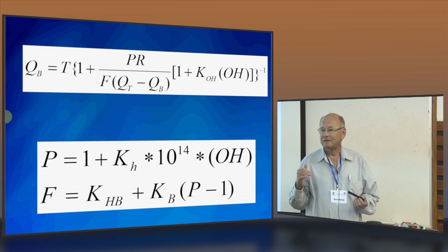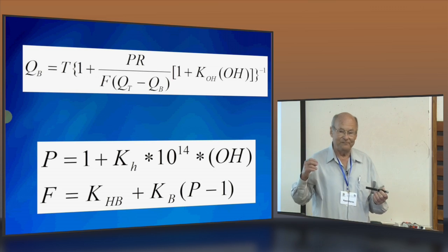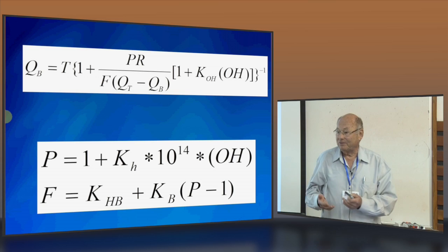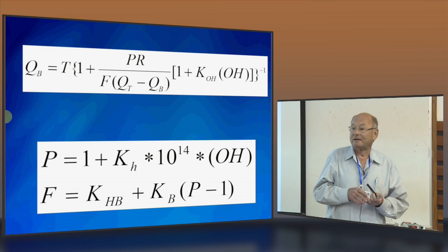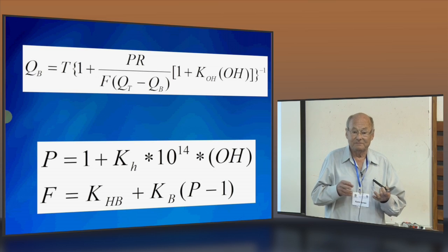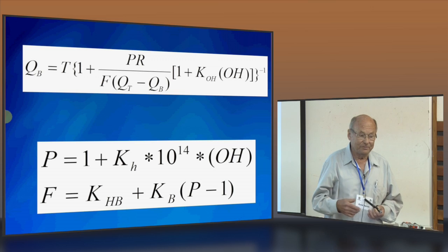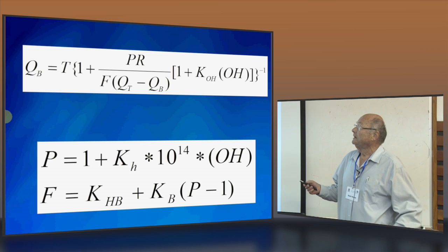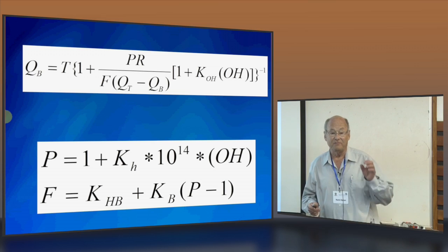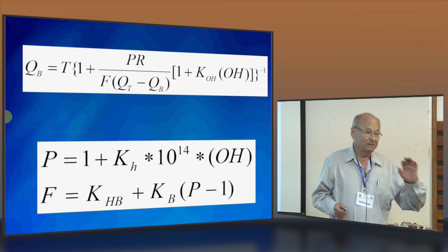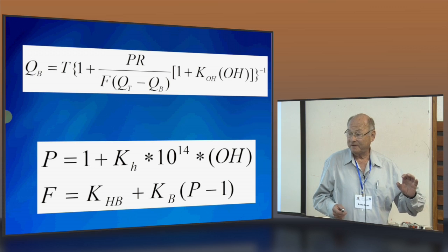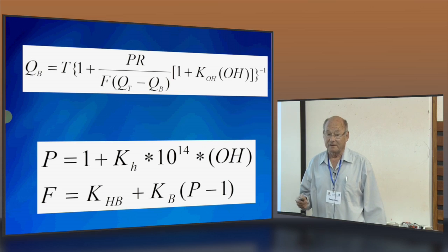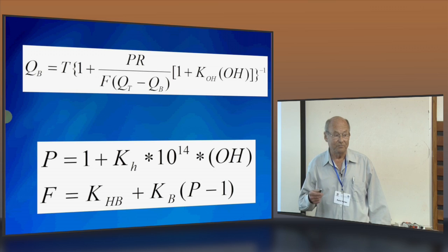There is nothing constant in fly ash, as well as in the treatment that we are doing in our field. It depends on the conditions, on the soil type, the type of fly ash, as well as some other factors that we will go through later on. Anyway, the amount that is adsorbed is a function of T, which is the number of sites available for adsorption on the clay surface, mainly on the clay surface, and a little bit on other constituents like iron oxide and aluminum oxide, etc.